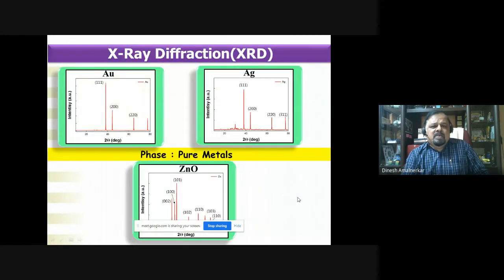These are X-ray diffractograms of Swarnabhasma, which revealed the presence of FCC, face-centered cubic, gold only. We didn't find any extraneous phase in that. It means it is a phase-pure material. We did not find any oxide or any other inorganic material. Within the detection limit of up to 3% for X-ray diffraction, we did not find any other material in Swarnabhasma.